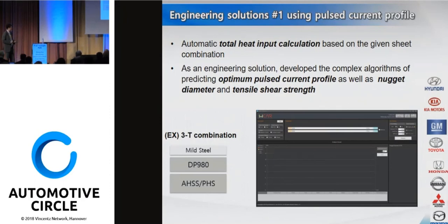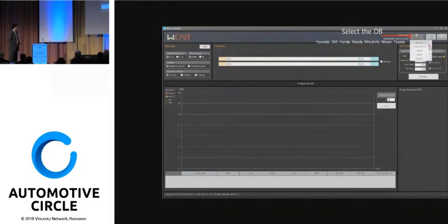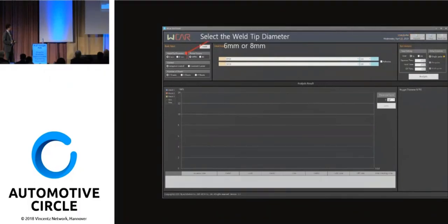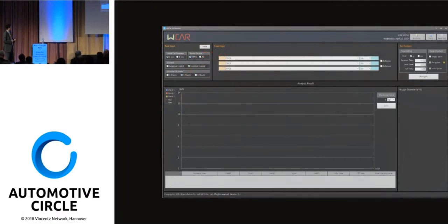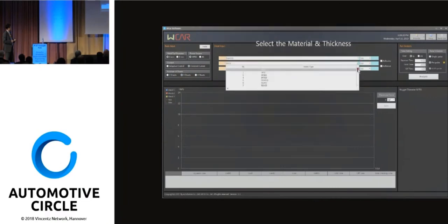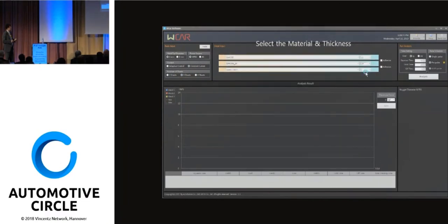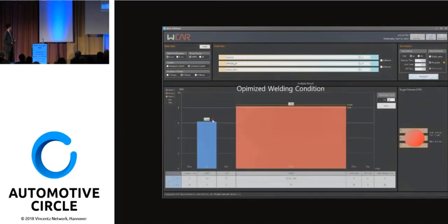This is the three-sheet combination I'm going to show here. We have about 8 or 9 OEMs' material databases here. So this is how it works. You select the OEM database and the tip diameter, select a 6-8 tip diameter, and any of the constant current or adaptive control, 3-sheet or 4-sheet combination, choose the materials and the thicknesses. You can also choose single pulse, pre-pulse, or multi-pulse, and then analyze it. It will come up with the optimum welding parameters with the nugget diameter.